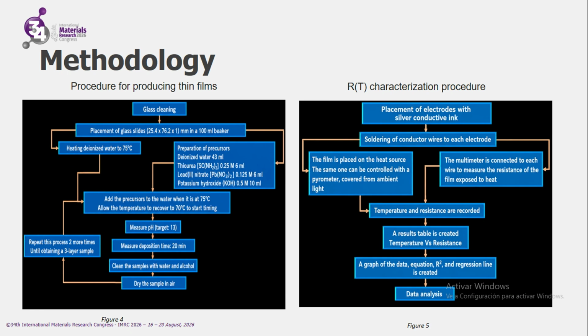Methodology, procedure for producing the film: glass cleaning, placement of the glass slide, heating the deionized water to 75 degrees. Preparation of the precursor: deionized water, thiourea, lead nitrate, potassium hydroxide. Add the precursor to the water, then heat it to 75 degrees. Allow the temperature to recover to 75 degrees to start stirring. Measure pH, target 13.